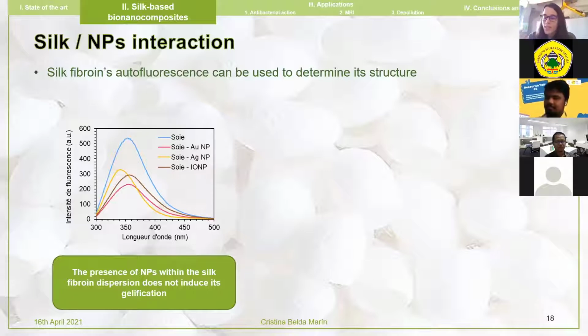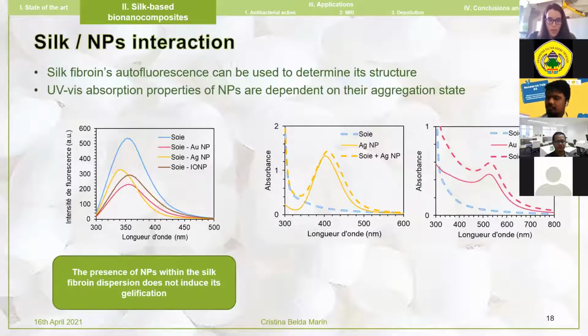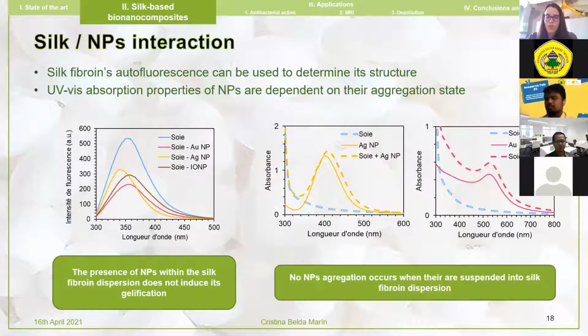So when adding nanoparticles into silk solution, we have a solution that's still liquid, so no gelification of the silk has been observed. As I told you, the properties of light absorption are very dependent on the nanoparticle size and shape. And so if an aggregation occurs when putting them into silk solution, we would see this through a change of the maximum absorbance. And as you see here for silver and for gold, it's not the case. So we still have the same maximum absorbance for both types of nanoparticles when they are included within silk solution.